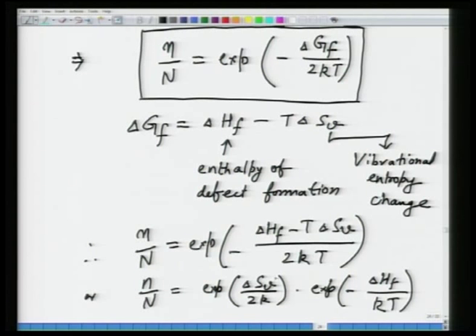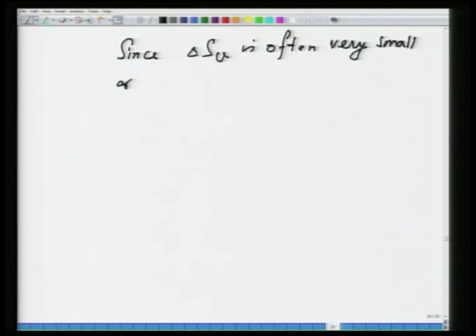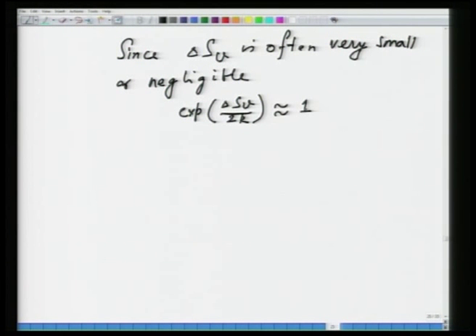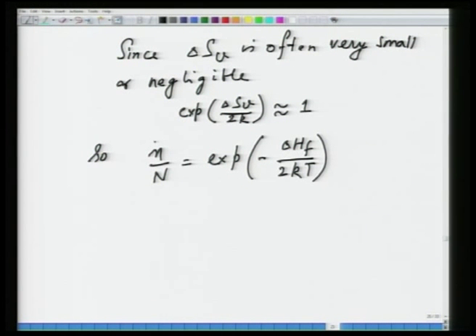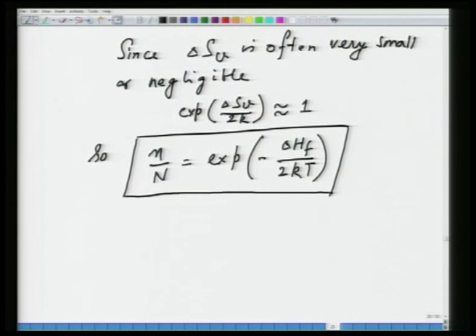2kT. Now, in most cases what happens is this entropy change is very small. So, this term is often neglected, since delta Sv is often very small or negligible, so exponential of delta Sv divided by 2k is almost equal to 1. So, n by N is equal to exponential of minus delta Hf by 2kT. This is your standard expression to calculate the equilibrium concentration of defects in a ceramic material or in an ionic solid.